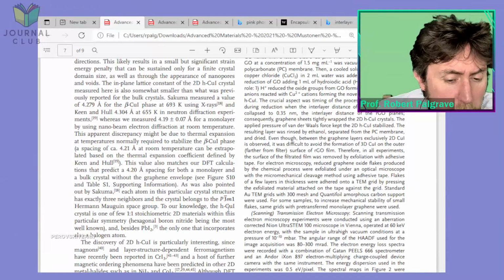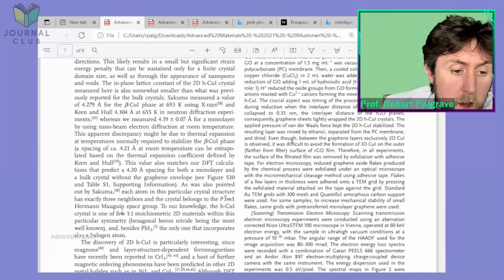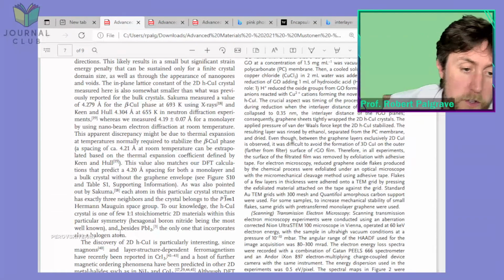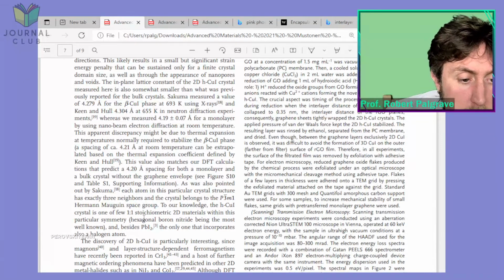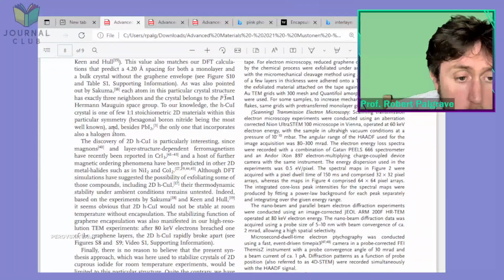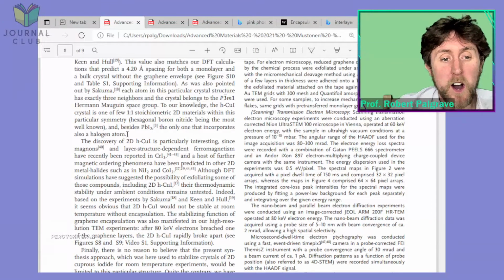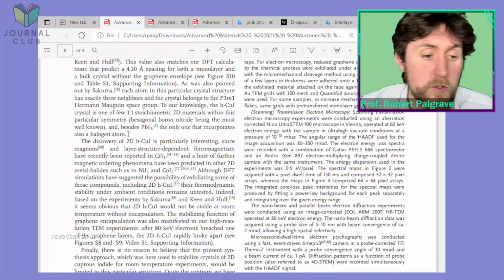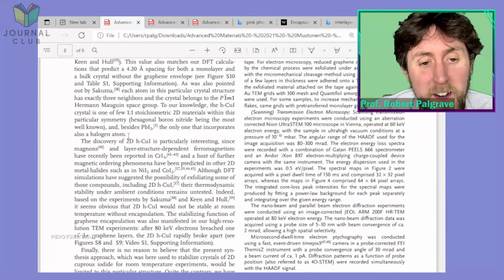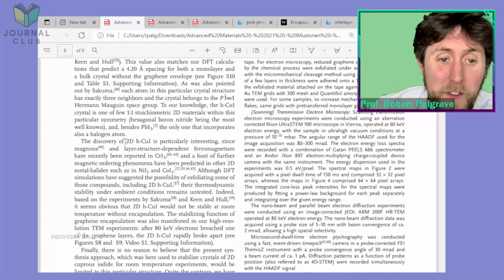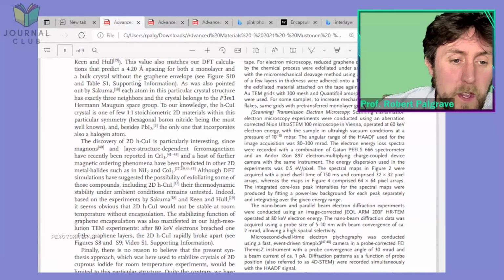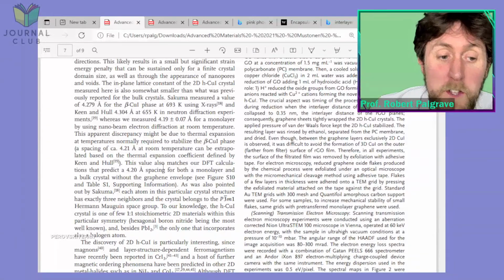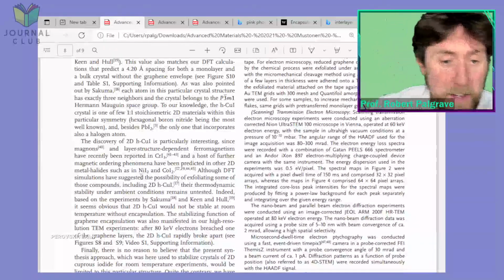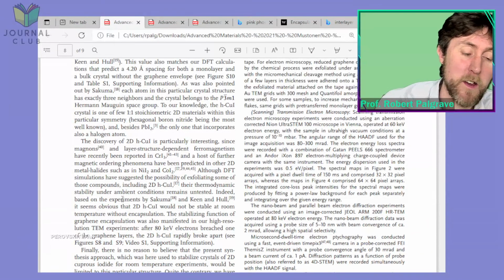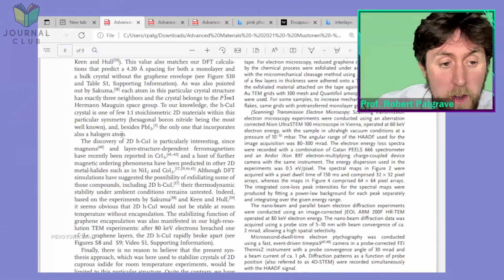Okay, to our knowledge, the hexagonal cuprous iodide crystal is one of few one-to-one stoichiometric 2D materials within this particular symmetry, hexagonal boron nitride being the most well known. And besides PbI2 it is the only one that incorporates also a halogen atom. Well, there's some interesting trivia for symmetry 3D space group fans. Cuprous iodide is one of the only binary materials with a 2D structure within this space group that has a halide anion, one of the only other ones being lead iodide. So there we go. That's kind of exciting, isn't it?